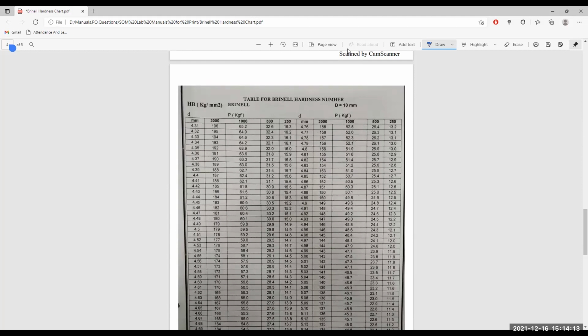Some more impression diameters are given in the Brinell hardness chart. Here we again take a 10 millimeter diameter indenter and apply 3000 kg, 1000 kg, 500 kg, and 250 kg respectively. For an impression of around 4.4, for the applied 3000 kg we get 187 Brinell hardness. For the applied 1000 kg load, for the same impression, we get 62.4 Brinell hardness, and for 500 kg 31.2, and for 250 kg 15.6.